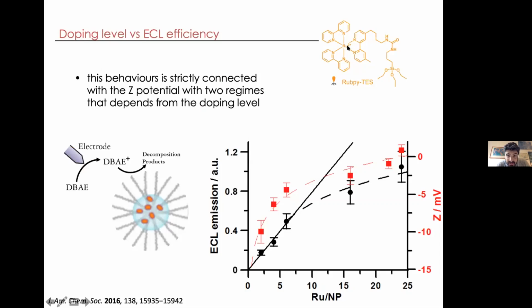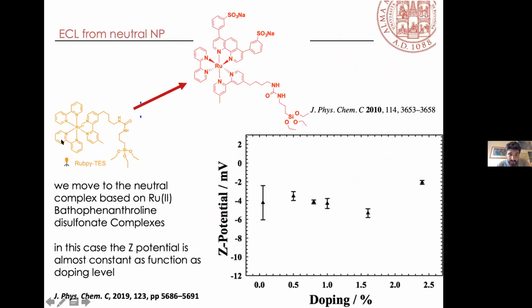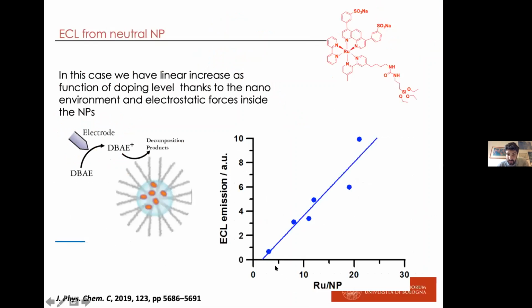Because ruthenium tris-bipyridine has 2 charges plus. So let's move from ruthenium tris-bipyridine to another inorganic complex that is a neutral one. So this is the bathophen complex. This is neutral. And in fact, if we increase the doping level, we still have a negative Z potential. If we go to our neutral complex and measure the ACL emission as a function of the dye doping, we have, in this case, a linear increase of the ACL emission, because Z potential does not change too much, and we can have this linear increase in the ACL intensity.